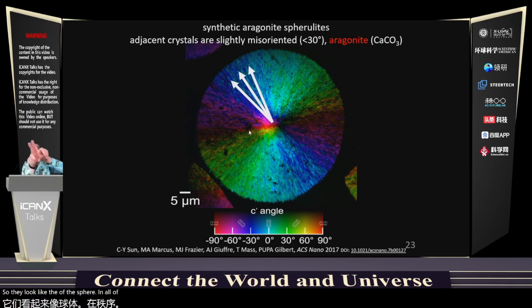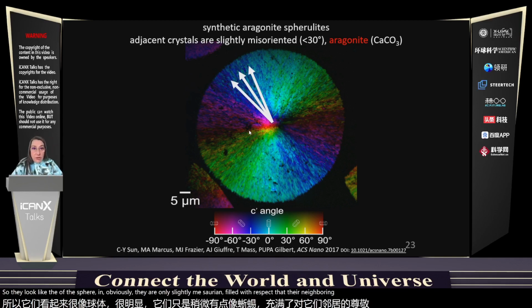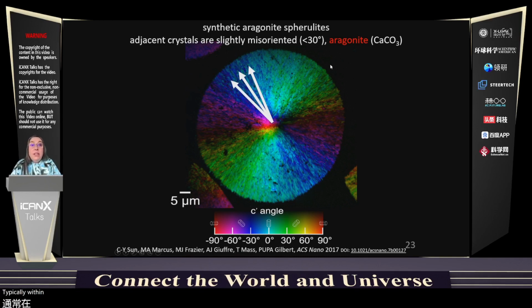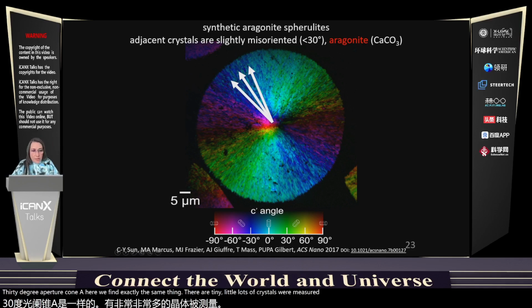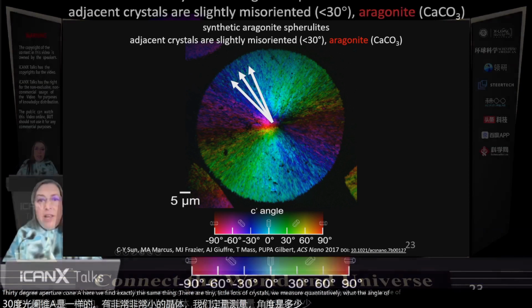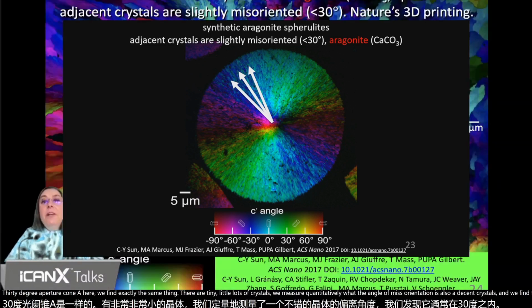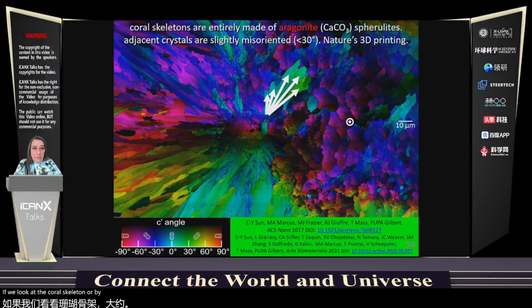And obviously, they're only slightly misoriented with respect to their neighboring crystal, typically within 30 degrees, just like nacre. Remember? 30-degree aperture cone. And here we find exactly the same thing. There are tiny little crystals. We measure quantitatively what the angle of misorientation is for two adjacent crystals, and we find that it's usually within 30 degrees.